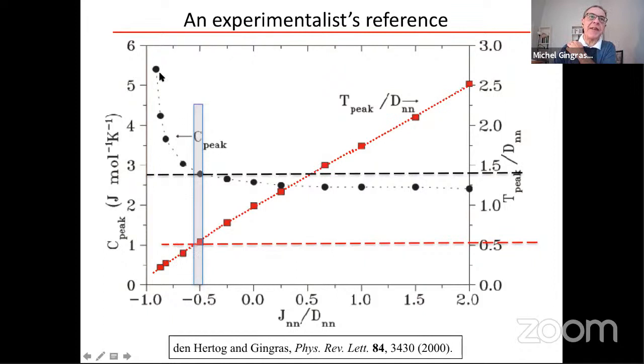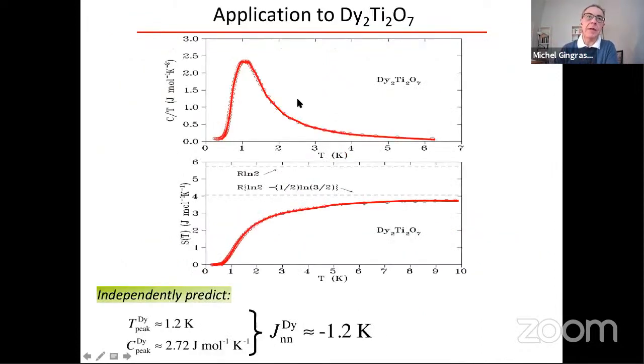And we can calculate the peak in the Monte Carlo simulation for that model by varying the nearest neighbor coupling J. And so what one finds for dysprosium titanate is that the peak for C is about 2.72 joule per mole per Kelvin, and the peak is at 1.2 Kelvin.